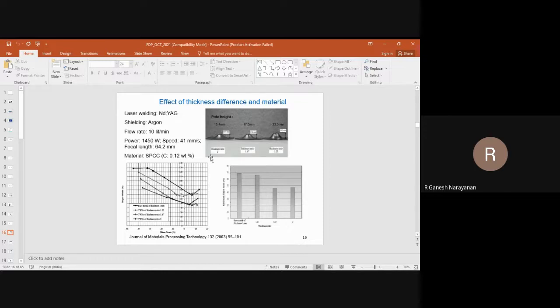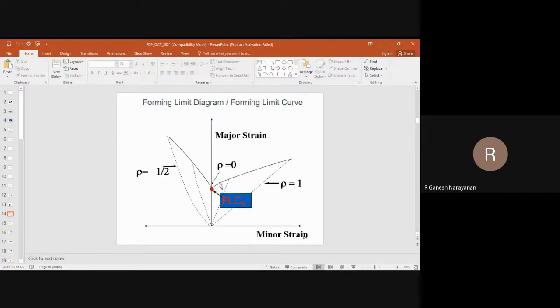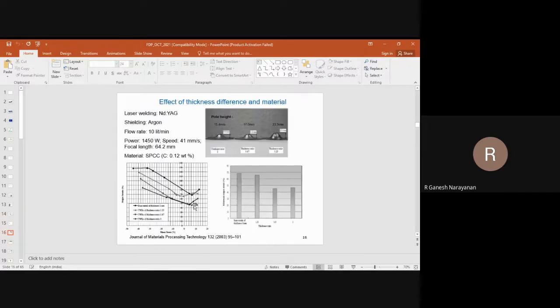Of course, the simplest way to explain the forming limit curve is the height of deformation. You will see that thickness ratio 2 has got 15.4, while on the other hand thickness ratio 1.25 has got a better dome or pole height, which means that it has got enhanced forming behavior. Right. This also will give you an idea. The bar chart on the right side shows what is happening to FLD0. The FLD0, this point, what happens to that? That is also increasing. You can see that it is also increasing.